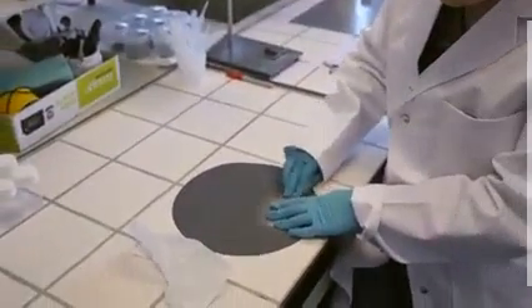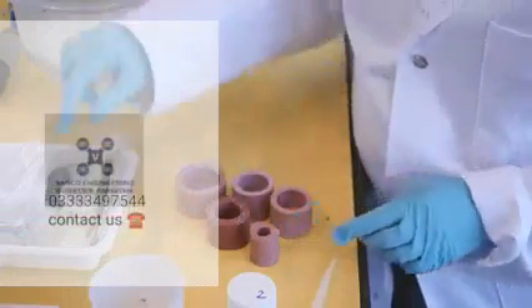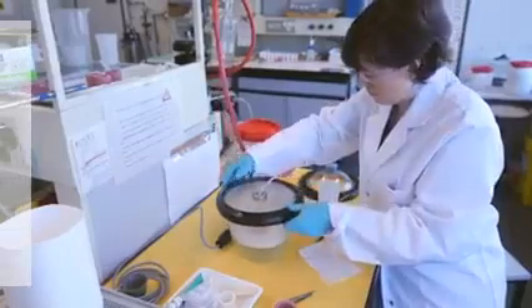It will first be polished with a 1200 grit sandpaper until a flat, shiny surface is obtained. You can then cut a small piece, and residual dust must be blown off. The sample is then placed in the mold to be resin coated. The molds here are homemade silicone molds, but commercial molds can be used. In order to avoid air bubbles, the samples are kept under vacuum during the introduction of the resin. However, you can also pour the resin first and then vacuum it to remove any air bubbles.